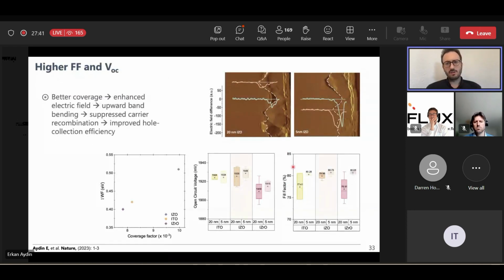And another thing we did in this work, we reduced the thickness of the recombination junction as low as possible. The idea was making a more resistive recombination junction, and also exploring the influence of the thickness, because we never asked ourselves why we use a thick IZO layer, why we don't use a thinner one, because we want to minimize the TCO as much as possible due to optical reasons. Then later on, we found in this work, 5 nanometer is working nicely and magically for our cells, but for other research groups, maybe the thickness range may vary between 5 and 10 nanometers, but in our case, 5 nanometer was the ideal one.